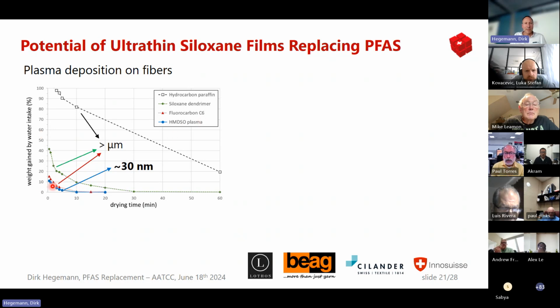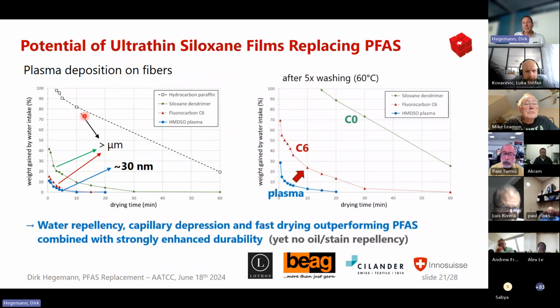The plasma coating dries quickly. The fluorocarbon C6 is comparable, but other PFAS-free substitutes we were looking at perform less well. And after 5 times washing, C6 is still acceptable. However, the plasma coating largely maintains good properties, and others, so C0 chemistry, show a lower performance. So indeed, we have a very good water repellency. It's related to a very high capillary depression, resulting in fast drying, which is even outperforming PFAS.